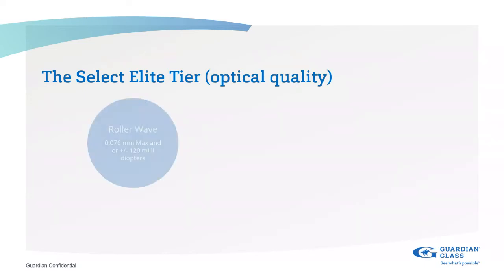Optical quality, obviously, when we're talking about roller wave, if you compare the European standard EN 12150 or EN 1863, they asked for a maximum peak to valley measurement of 0.5 millimeter. Now, for the Select Elite Fabricator, we are looking to reduce that to a maximum of 0.076 peak to valley, or plus or minus 120 millidiopters from the automatic scanner. As you can see from there, we've actually reduced the roller wave quite dramatically from the actual international standard requirement.